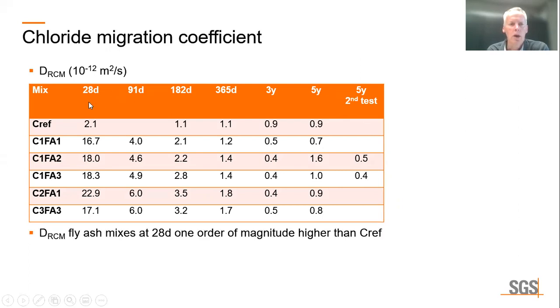If we then take a look at the results after 28 days, we see that all fly ash mixes show migration coefficients which are 1 order of magnitude higher than the reference concrete mix.